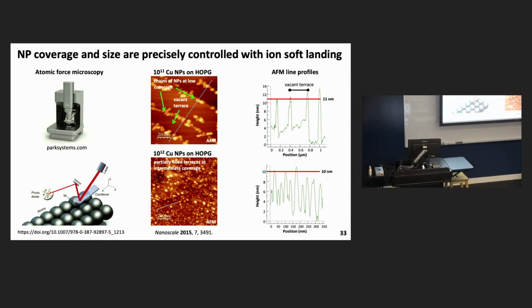So you end up at low coverage, basically, what happens is the ions go down stochastically, they sample the whole surface, and then they find that step edge where they get stuck, right? And then they form these extended chains. And that's what you see here.